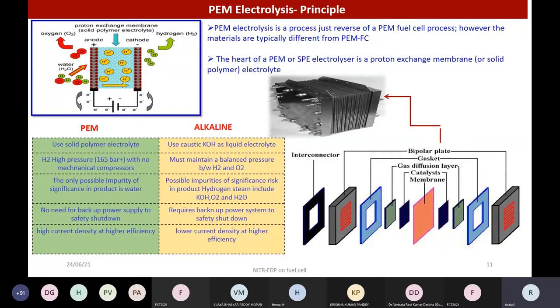Whereas in the case of electrolysis, on the cathode side, you can use some carbon supported catalyst and carbon flow field plate. But on the anode side, you cannot use any carbon based material, because the operating voltage is a bit high, 1.6 volt. At that potential, in this acidic aqueous medium, the carbon will easily undergo corrosion. So in order to avoid carbon corrosion, we must use non-carbon based material, especially titanium, which is widely used for the cell construction.